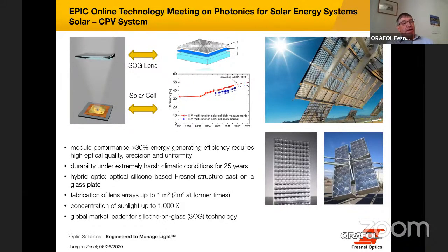This means extremely good conditions for the glass. So we combined our microstructure with a silicon layer to glass. This means the glass was very stable, and this structure was mounted on the glass, and the structure was very, very helpful to have at the final end a very high performance of this module.